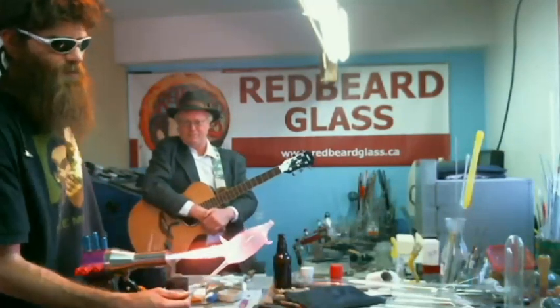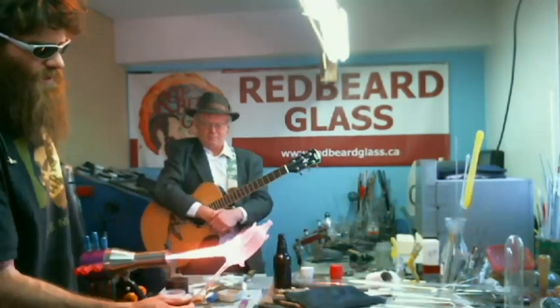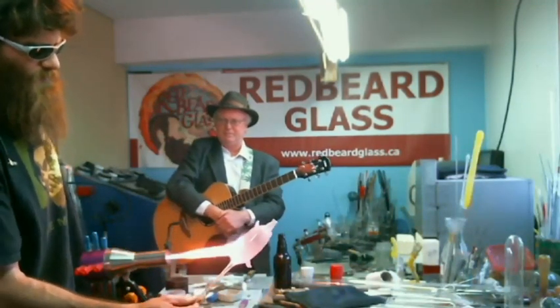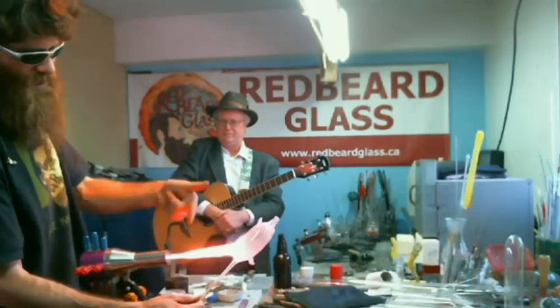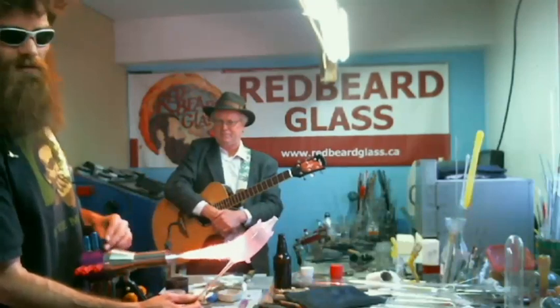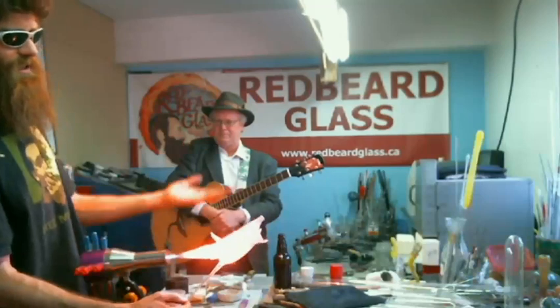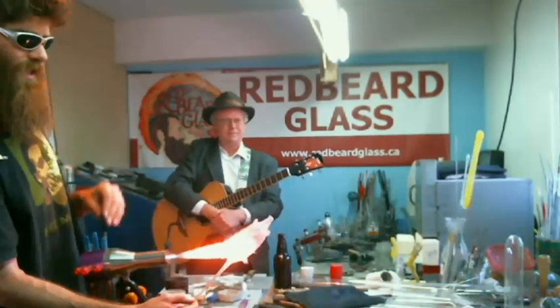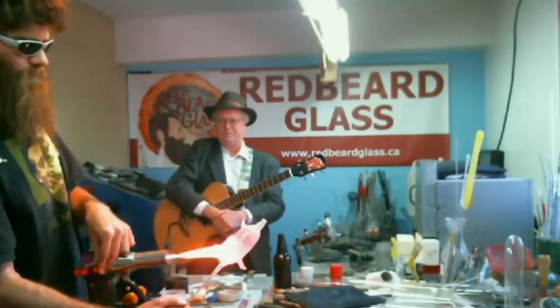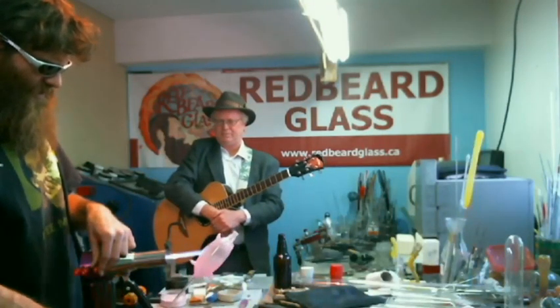This is a good lesson for any of you glass blowers, you beginners out there. Believe me, you're gonna crack some stuff. So the first thing you do when something cracks is you get a big bushy flame on it. Maybe even deposit some carbon, really bushy. And what you're doing here is slowly heating the glass up and closing that crack. Now I'll go down to a pinpoint and voila, that part of the crack is gone.